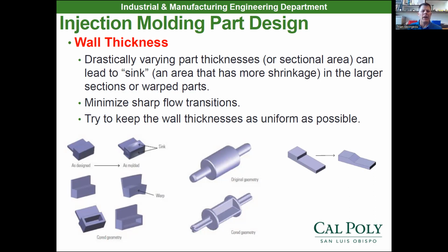But looking at the bottom there, on the bottom left, you can see this part will sink and it can warp because you have a large mass of plastic in one zone and then a really thin mass of plastic in the other. So the thin part's going to solidify at one point. The thick part's going to take a lot longer, and it's going to move around and change size when the thin part's already solidified. You're going to have a warped part and most likely sink on the actual surfaces. Sink just means the surface is sunk when it's solidified, because all the material kind of shrunk down and caused that surface to sink down.